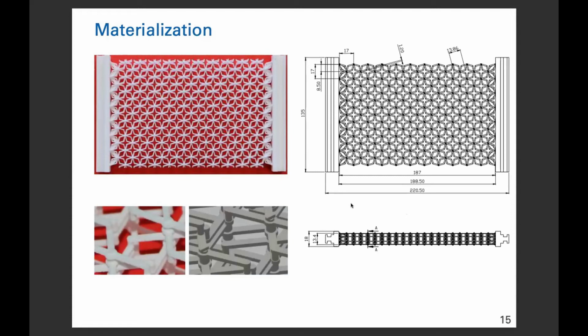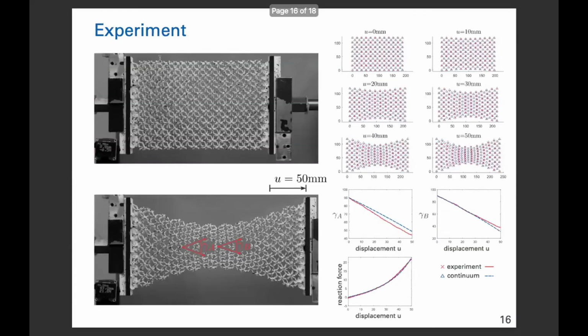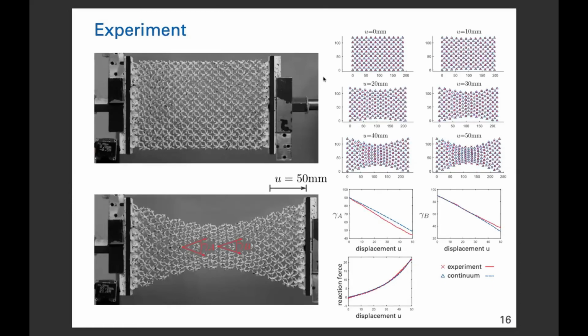And in order to avoid any out-of-plane buckling, we added 4 such layers, and then everything was printed with PMMA, and then tested in a bias extension test. And here you can see the results of the experimental digital image correlation with the finite element model, which was done with a mixed finite element formulation. So we used Lagrangian elements for the placement and also for the deformation, and we coupled it with a Lagrange multiplier field.